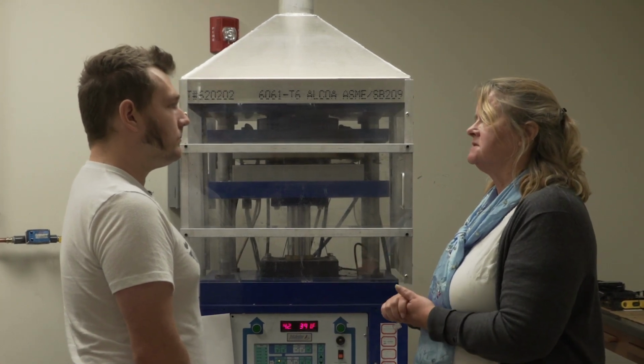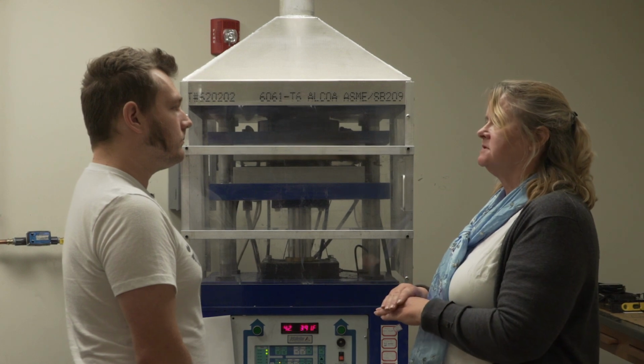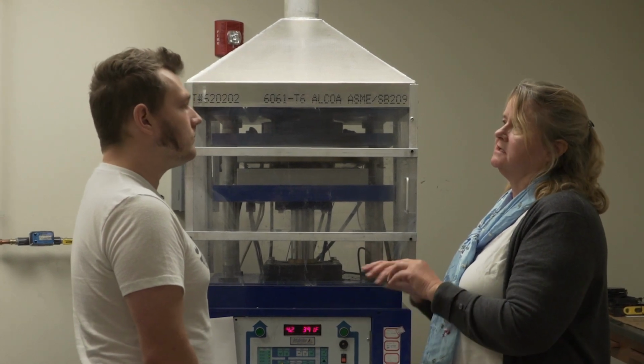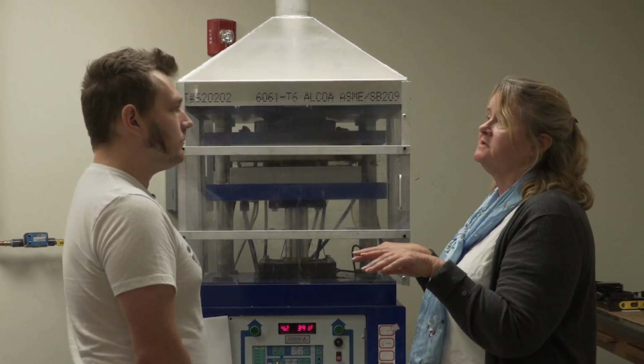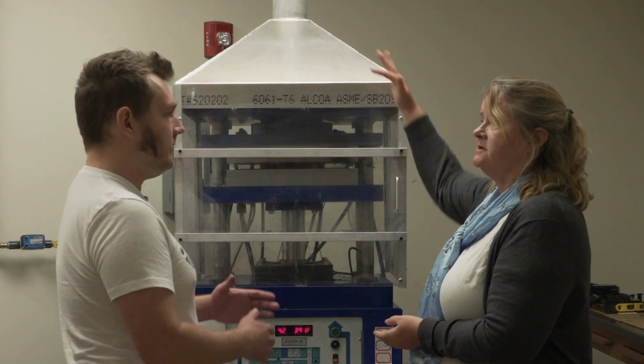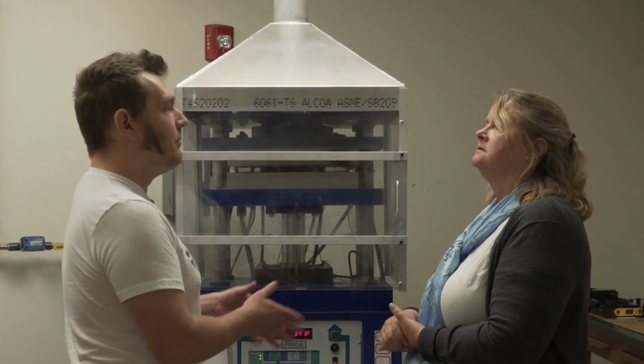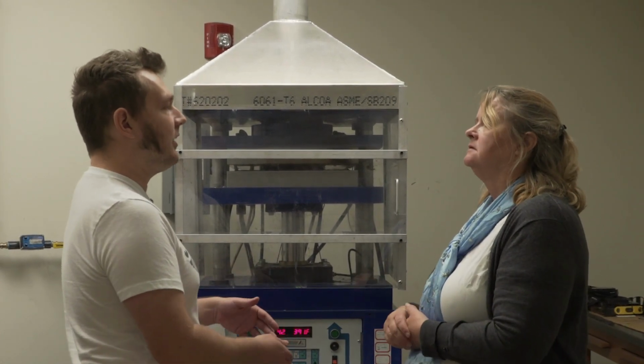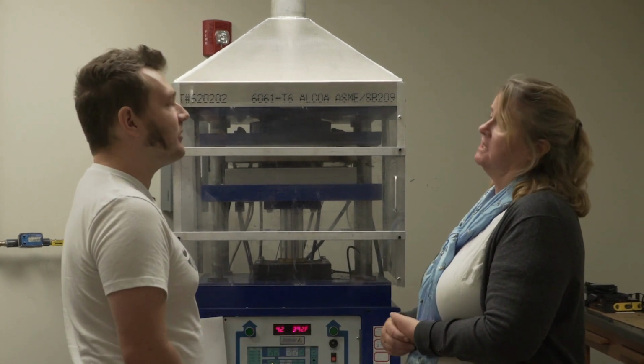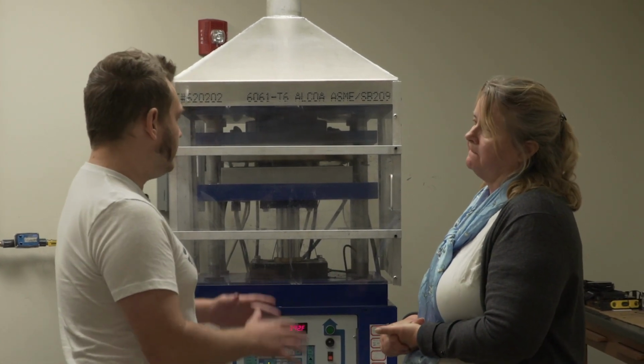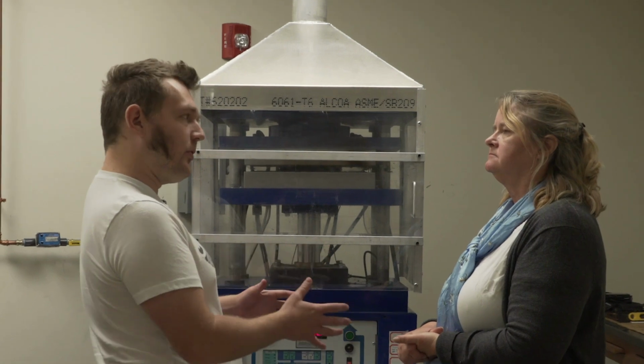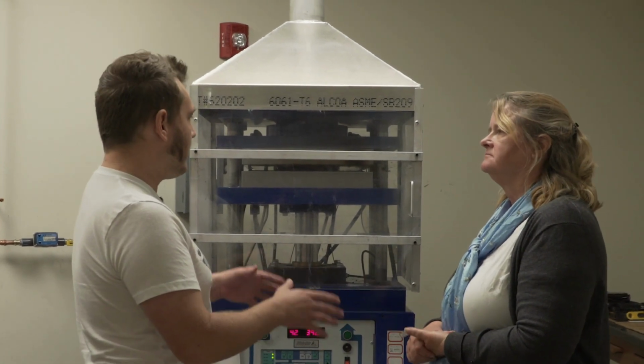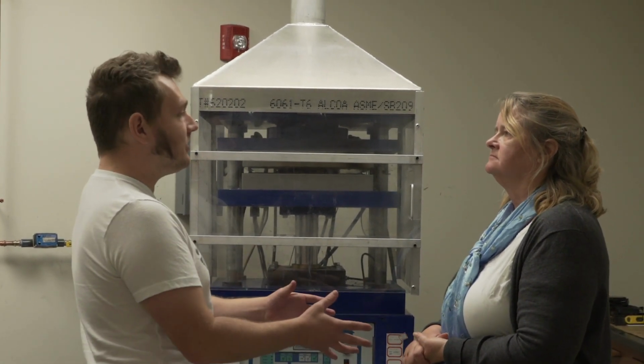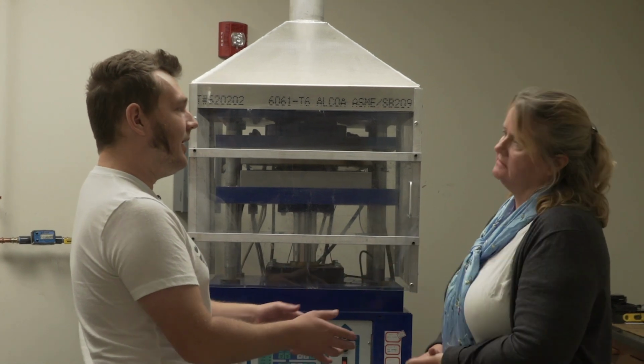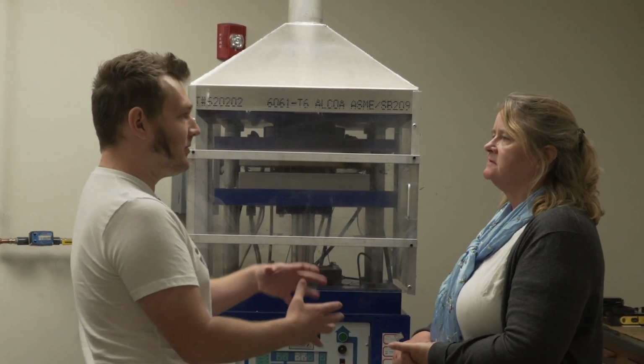So we're well above that state, and when the press releases, it's no longer sealed, and the supercritical fluid will seep out through the sides of the mold and up into the vent. So basically, the leakiness of the mold when you release the pressure is what starts the supercritical extraction. Yes. And you said these are pressures up to about 2,000 psi in there? So essentially the mold in the hot press is your supercritical dryer. Exactly. It's just made in 3 pieces instead of 1.